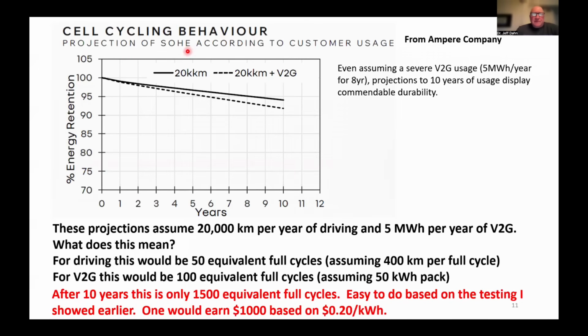So this is a graph which they presented to give a projection of how the energy retention in the cell will vary with years of use. Okay. So for their cell type, if you drive 20,000 kilometers a year, you would follow this solid line. And after 10 years, you have about 94% of your original energy remaining. Now, you might think, okay, that's probably an overestimate, but no way. From the data I showed you before, this should not be surprising.